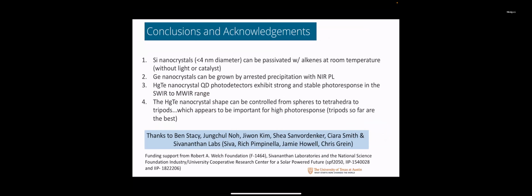So in the case of mercury telluride, even though it's fairly straightforward to make colloidal nanocrystals of mercury telluride, and you can manipulate their shape a little bit, the details of the ligands actually have a major impact on the performance of that material. In the case of silicon, it's really a challenge to just synthesize the materials, and the same is probably true of germanium. But in all the cases, the ligands are having a dramatic impact on the optical properties of the materials.